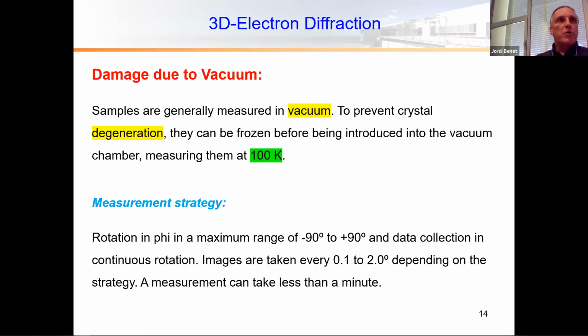Then in relation to vacuum damage, especially for pharmaceuticals, where you have hydrates or solvates, or molecules which are quite volatile, they would be destroyed quite quickly in vacuum. But we can prevent this by freezing these crystals before introducing them into the vacuum chamber, cooling them down to 100 Kelvin.